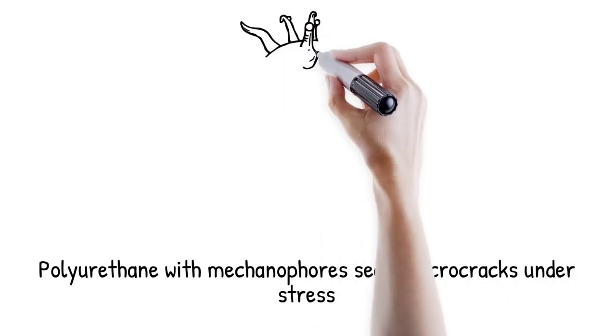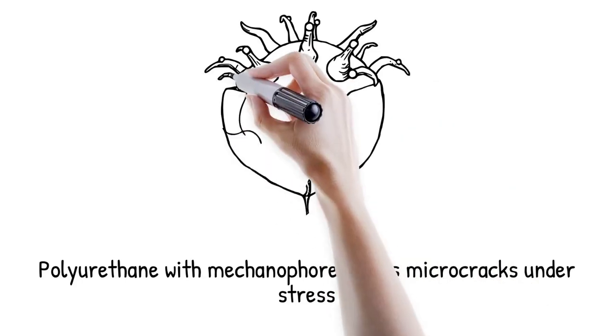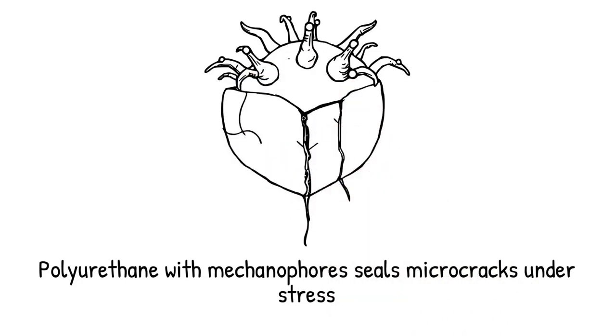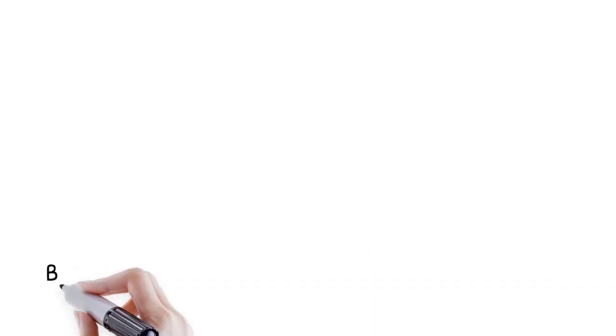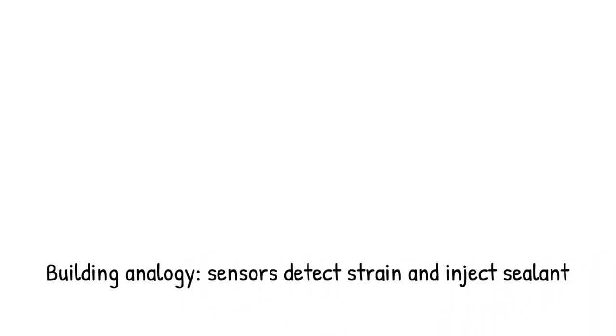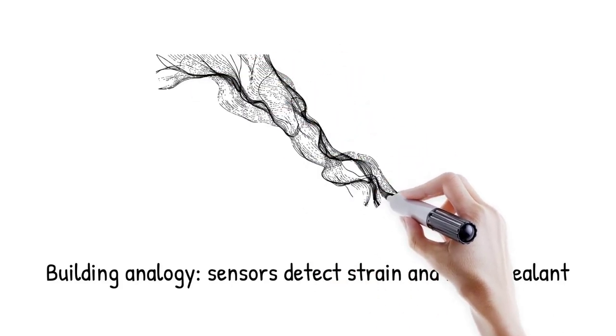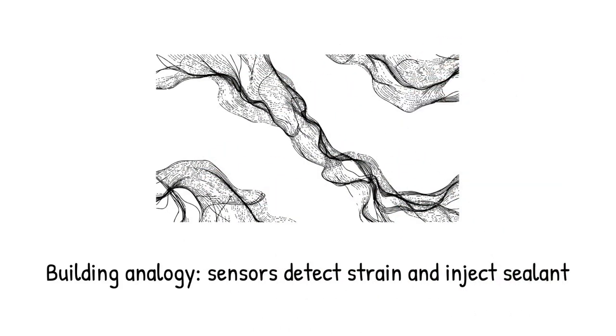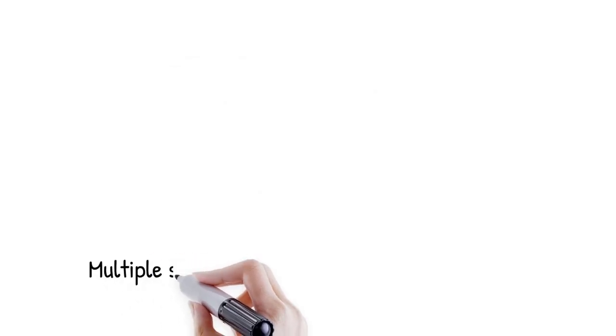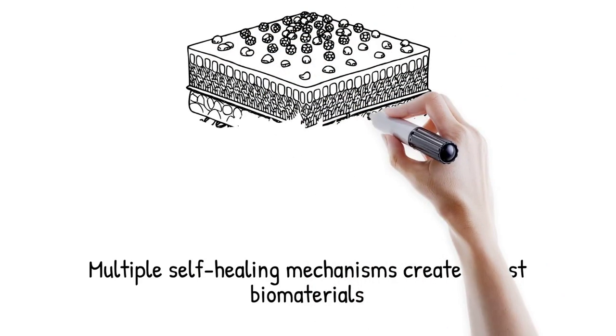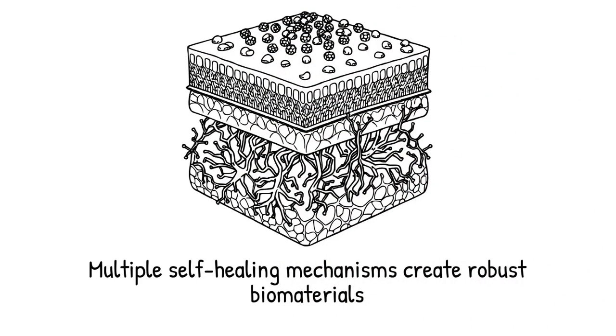A polyurethane containing spiropyran mechanophores released a healing monomer under 10 MPa of stress, sealing micro cracks without external cues. It's like a building whose structural sensors detect strain and automatically inject sealant into developing cracks, combining multiple self-healing mechanisms across length scales. From molecular bond exchange to macro-scale vascular networks, yields robust, multifunctional biomaterials.